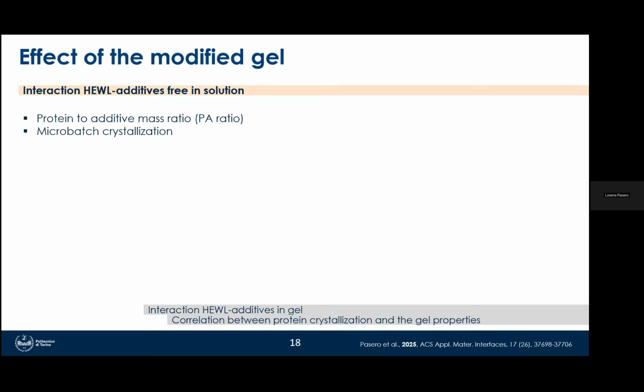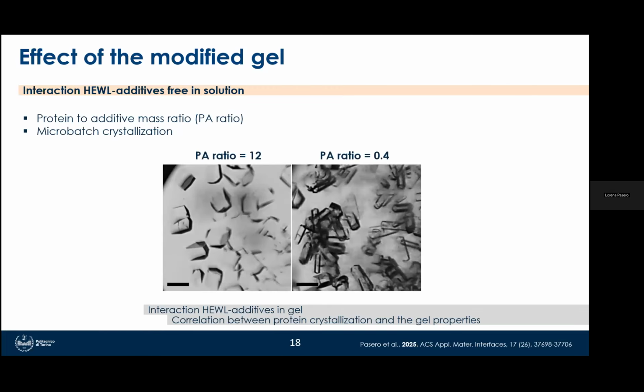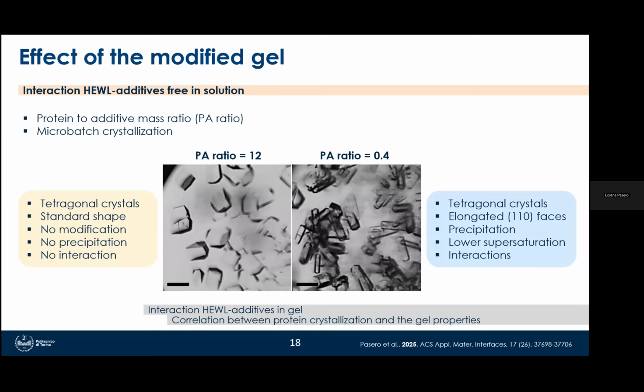And we compared a ratio of 12, which was the same used in the gel, and a ratio of 0.4, where the concentration of additive was higher. In the first case, crystals maintained the tetragonal standard shape, and no alteration was observed compared to the additive-free solution. An increase in additive concentration instead led to tetragonal crystals, which displayed elongated (110) faces, which are typical of lower